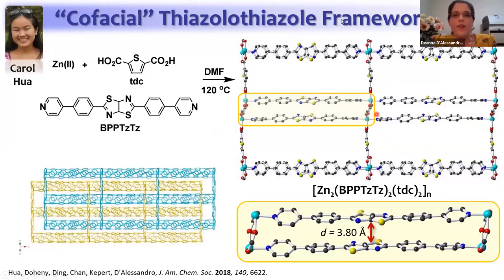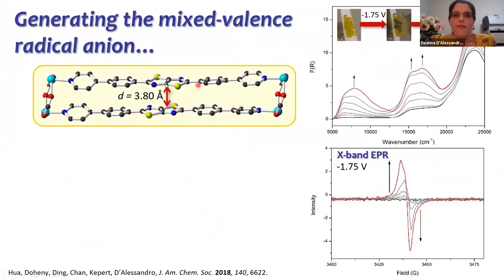And if we reduce this metal organic framework, remembering that the thiazolo-thiazole can exist in either radical anion or dianion state, here we apply reductive potential minus 1.75 volts. We see the formation of these new bands in both the near infrared and visible region. And the compound correspondingly changes to this dark forest green coloration. So these bands here in the visible are due to the radical anion of the thiazolo-thiazole, and that's confirmed with solid state EPR spectroelectrochemistry. But this band in the near infrared is really quite interesting.